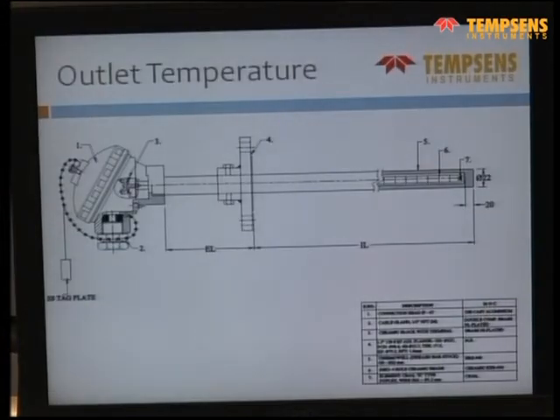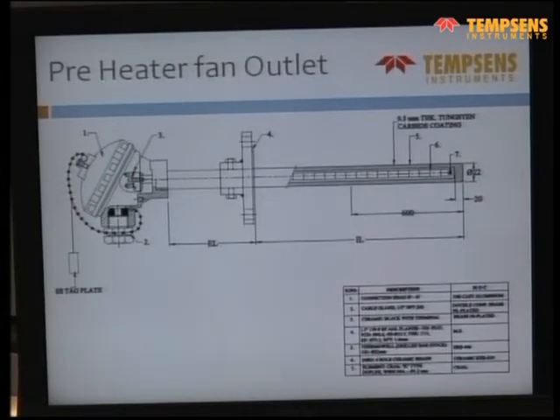In the case of the cement industry, this is at the kiln outlet temperature. This is normally made of HRS 446. It's a high temperature withstanding material, and inside can be an MI cable of SS310 and K-type element. And the life here you can expect about 1 month or 1.5 months for such a thermowell. In this case, the life would depend on how long your thermowell can withstand such an aggressive and high temperature application. Aggressive in terms of abrasive, because the clinker is touching and it is of high temperature and very abrasive nature, so it eats away the outer protection tube. This is again mainly HRS, and can also be coated with tungsten carbide.